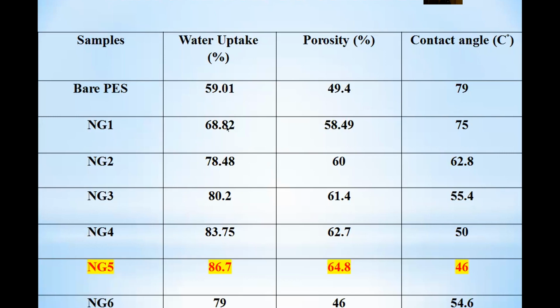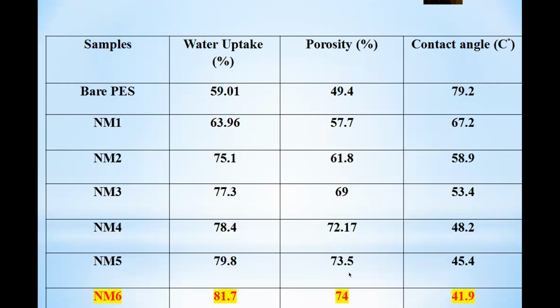and porosity increases, and contact angle decreases, indicating increasing hydrophilicity until the optimum in NG5. In this table, the effect of increasing titanium is the same. Increasing the titanium dioxide concentration, water uptake and porosity increase, and contact angle decreases, where hydrophilicity increases.